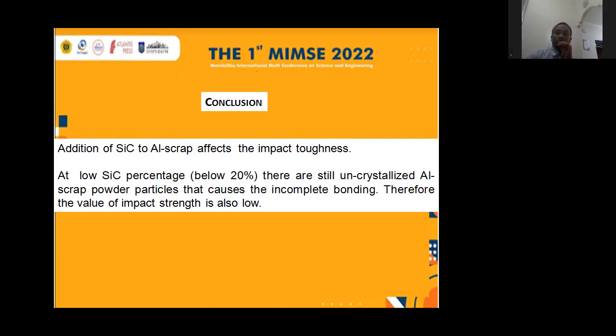And then, as the conclusion, the addition of SiC to aluminum scrap affects the impact toughness according to the experimental results. At a low SiC percentage, or below 20% of SiC, there are still uncrystallized aluminum scrap powder particles that cause incomplete bonding. Therefore, the value of impact strength is also low.